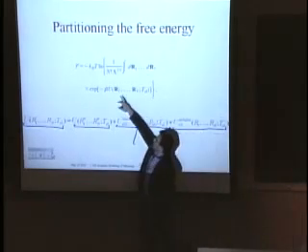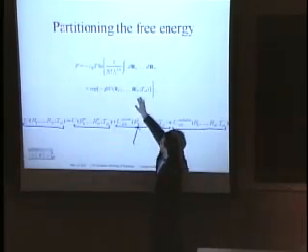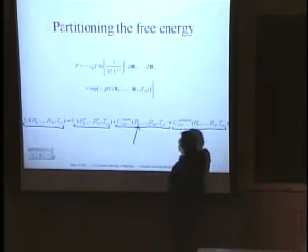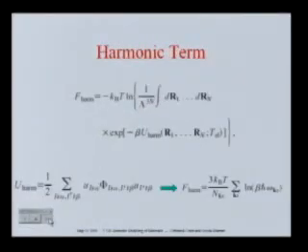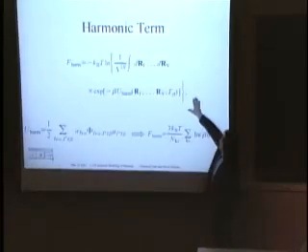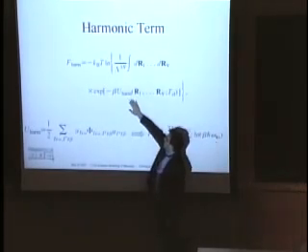Because you have a logarithm of an exponential, if you break this into a sum of different terms, all the terms contribute separate free energy pieces to your overall system. So we could calculate, say for a solid system, the additional vibrational free energy that comes on top of the equilibrium ground state energy, coming just from the harmonic term.